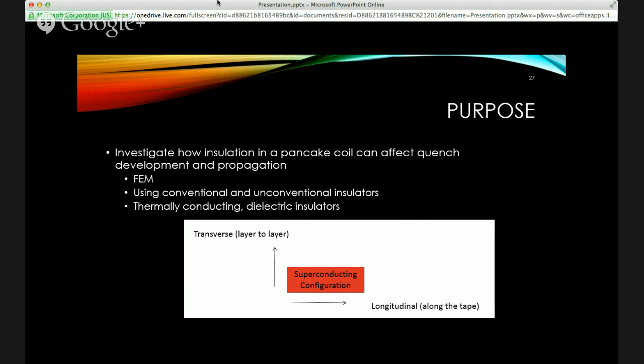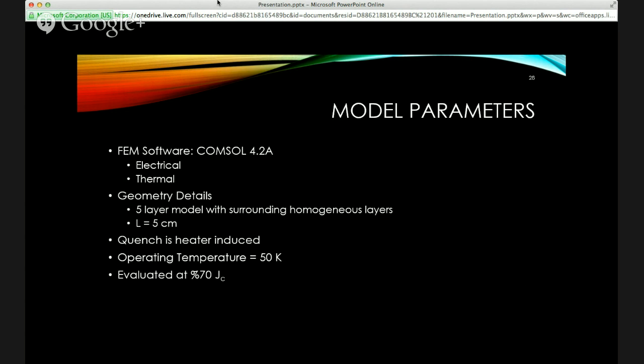So this is a little diagram. So if you're looking at the superconducting configuration, I mentioned how quench tends to propagate along the tape, which is the longitudinal direction. So what also happens in the transverse direction, which is that layer-to-layer direction? So COMSOL is my software. That's where my heart is. I've become quite fond of it over the years. If you can hear the sarcasm in my voice.